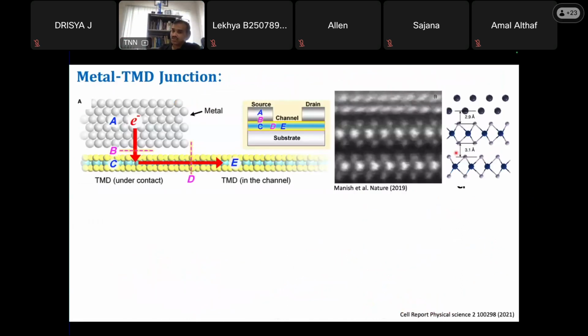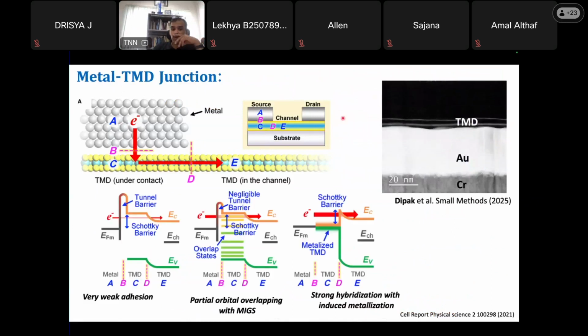There can be several types of defects in it. It can be sulfur vacancies in MoS2. It can be molybdenum vacancies, depending upon the synthesis strategy you are following. If this defect level gets pinned, then the Mott-Schottky relation will also not be followed. So you cannot directly choose the metal like that. This is what I said, partial orbital overlapping is because of Fermi level pinning. If you end up pinned, the energy levels get pinned into certain energy levels.